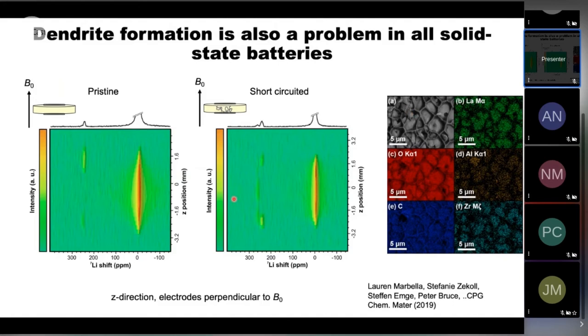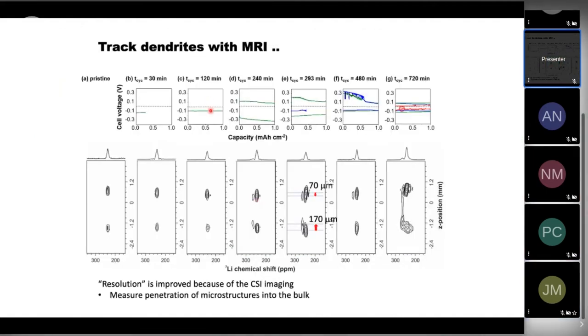So these are some of our early MRI studies showing that even in a solid state battery, if you don't optimize the way that the composite is formed, you can still form these dendritic structures or mossy structures that completely envelop the ceramic particles, in this case of LLZO, or lithium lanthanum zirconate. And you can track the formation of the mossy structures in this very faint pattern here by magnetic resonance imaging. And you can then ask, how do the dendrites or the mossy structures grow with time, and relate that to the electrochemistry that's being seen.